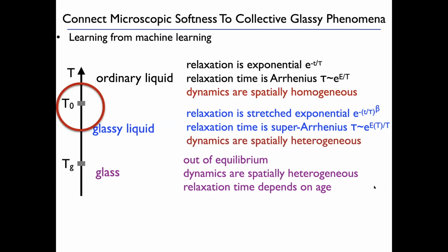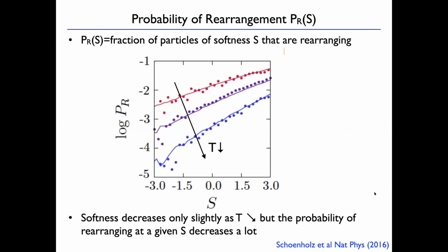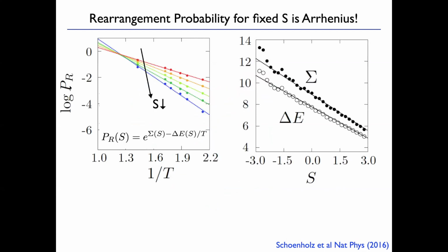All right, so first I'm going to concentrate on this onset temperature. What I'm going to calculate is, for particles of a given softness, what fraction of them are rearranging at a given time, and then look at this on average. So for particles of softness S, what fraction of them are rearranging? I call this the probability of rearranging. And we can plot the probability that a particle is rearranging, for a fixed softness, as a function of 1 over the temperature. So I plot the log of this as a function of 1 over temperature.